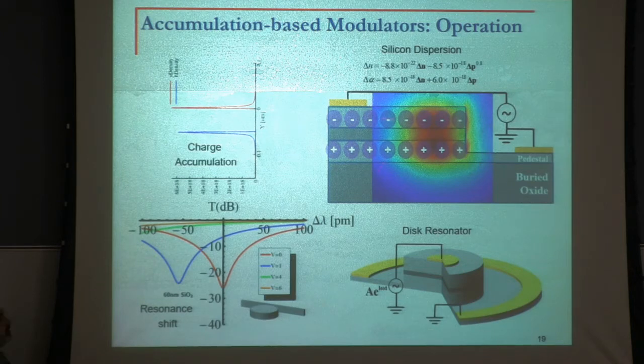Now, the advantage of this structure is multifold. Number one, I can clearly see that by not requiring a PN junction and a current, I can reduce power consumption. Two, I will have a trade-off between the capacitance, which tells me what voltage can be applied. So I want some charge. Large capacitance allows me to work with very low voltages, and a small capacitance allows me to work with large voltages. Large capacitance has a larger RC, lower speed. Small capacitance has a smaller RC, higher speed. So there is a trade-off that I can play with using this structure.